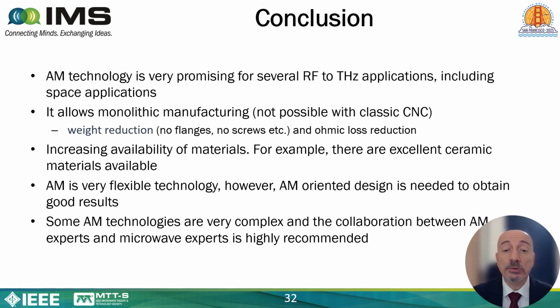And consider that this is not even possible with classical CNC technology, the computer numerical control technology, such as, for example, the classical drilling process. And this is very important, and this is a very good result, because in this case we are able to reduce the weight of the component, because we don't have any assembly flanges, we don't have assembling screws, and we also reduce the ohmic losses, because when you join two metal parts, there are problems with the ohmic contact generally, and this creates losses. So it is better also from this point of view.